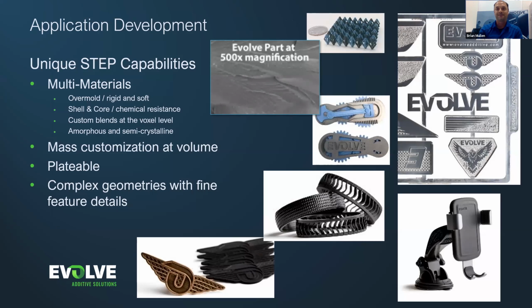We've created some really nice, amazing demonstration parts that you guys can see. So our materials, as I mentioned, can be printed in multicolor. So this was done within one build. We have blue ABS, we have black ABS, or these could also be thermoplastic elastomers. Alongside a support, which is dissolved away, we end up with parts, some of which have gears in them that can be moved. We also, because ABS is very well known to be chrome plateable, can make a series of custom automotive and different badges with our materials. And then we can also create fully functioning parts like this cell phone holder here. This is all made within one build within our step process.